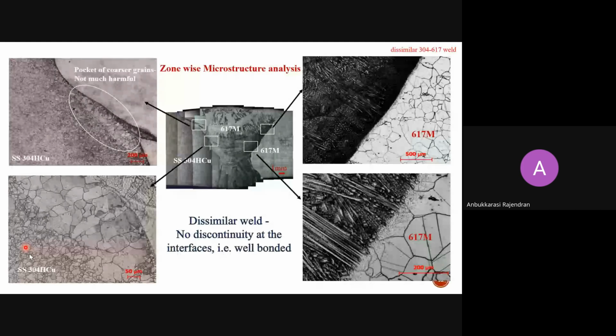Some regions have fine grains, and close to the weldment there are coarser grains due to the heat affected zone. Whereas on the other side, there is no heat affected zone, and such coarser grains we are not seeing here, as both the weldment and the base metal are the same material, right? So the dendritic growth in the weldment is also seen clearly. As I mentioned, most of the information we can get from the optical micrograph. If our sample preparation is good, we can get the complete idea of the microstructure from the optical micrographs itself.